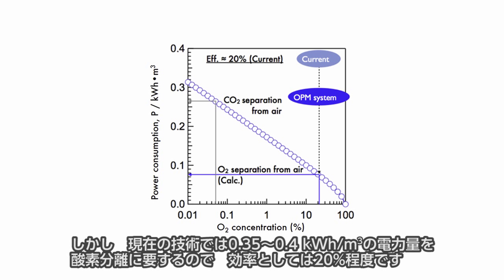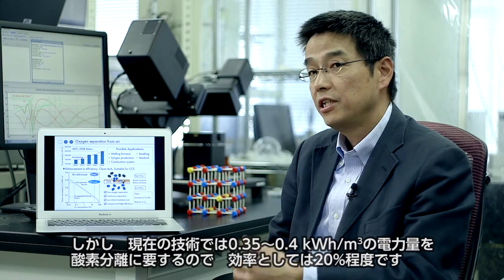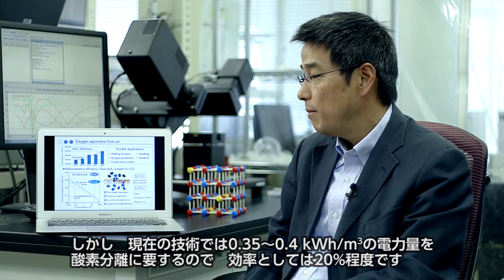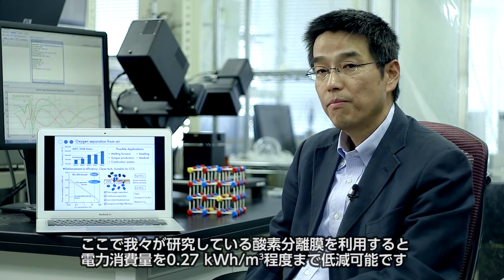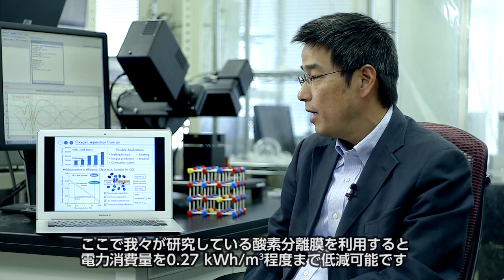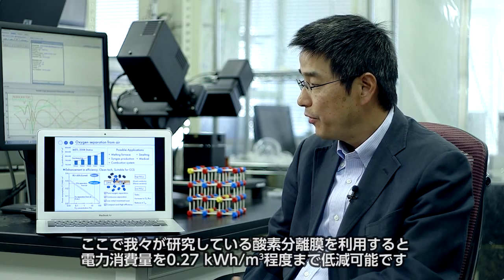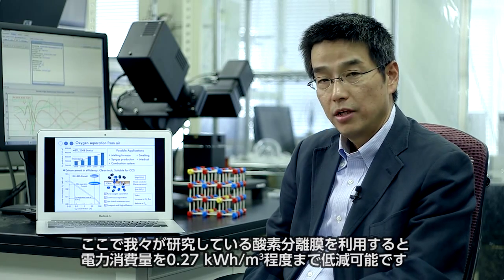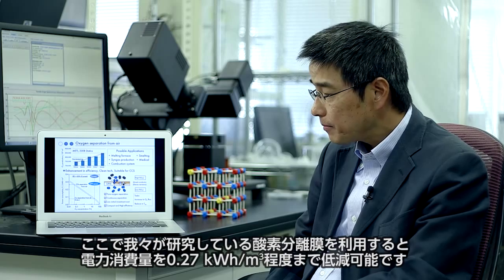But at this moment, current technology requires 0.35 to 0.4 kilowatt-hour per cubic meter, meaning efficiency is only 20%. But by using the oxygen permeation membrane that we are doing research on, the energy consumption can be reduced down to 0.27 or something like that.